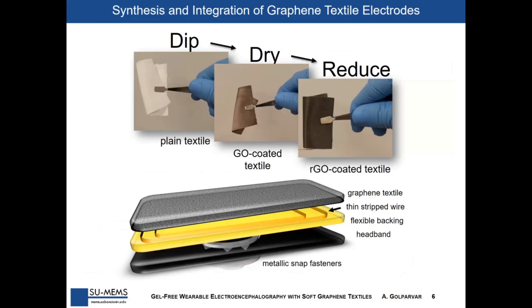Well, in this study, we prepared graphene textile following a previously introduced scalable three-step dip, dry, reduce process. This fabrication process starts with graphene oxide preparation, and then we immerse the plain textile in graphene oxide solution. After that, each of the coated layers was dried to achieve homogeneous graphene oxide coated textile. Later on, thermal treatment and chemical reduction were carried out to create a conformal electroconductive graphene structure.